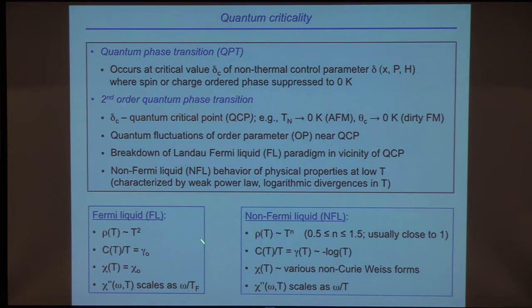So if you look over here, you see how a Fermi liquid behaves. Resistivity goes as T squared, and then specific heat and susceptibility approach constant values. And the imaginary part of the magnetic susceptibility, which you would measure, say, for neutron scattering, scales like energy over the Fermi energy, or frequency over the Fermi temperature. It's the way it's usually expressed. But in a non-Fermi liquid, this exponent can range between 0.5 and 1.5. It's usually close to 1.